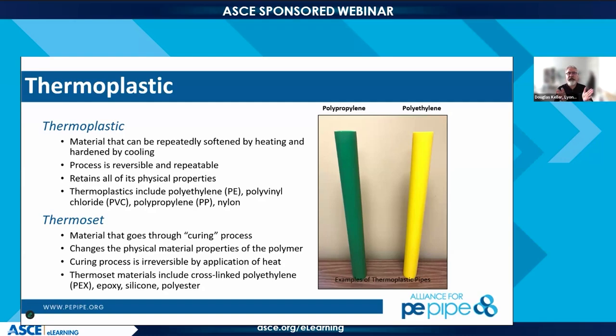So what this allows us to do is to take those pellets that are cold, heat them up, make pipe, send the pipe to you. We then fuse the pipe together by heating it up again, cooling that joint down, and now you have a monolithic piping system. So it is reversible and repeatable. The polymer maintains all of its physical properties during this melting and cooling phase. So there's really no change to the polymer in the number of times that you would typically expect for heating and cooling to occur. So typical thermoplastics, as I said, polyethylene, PVC is a thermoplastic, polypropylene, and then the polyamides, which includes nylon, are also thermoplastics.